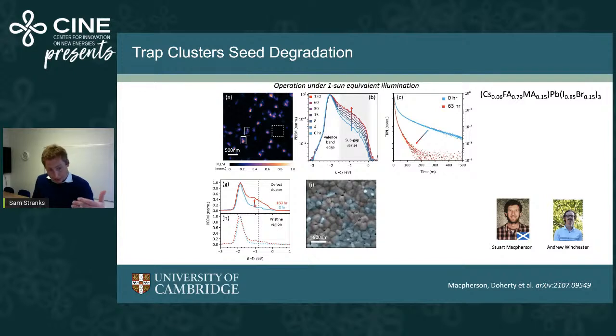What we see is this subgap density of traps really increases much, much more, on both a relative and an absolute scale, than a more pristine region, such as this one, where we don't have traps to start with. We don't see much of an increase in the subgap density of traps. So this is a really important result, because it's saying that where we have these initial traps, that's where the degradation seeds, and that's where the degradation starts to happen. And we can actually see that when we look at this SEM image of a degraded film. We've run them for many hundreds of hours, and overlaid in blue is the initial trap distribution. What you see is that wherever you see these traps initially, by and large we see degradation, we see pinholes forming in these samples. So again, that's showing that these trap clusters are acting as seeds for degradation.